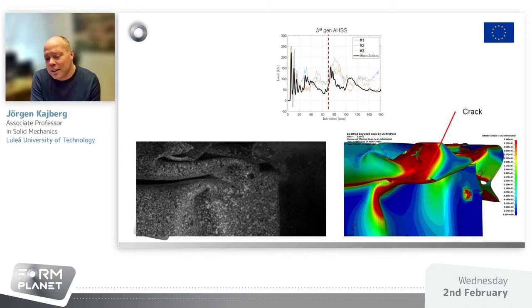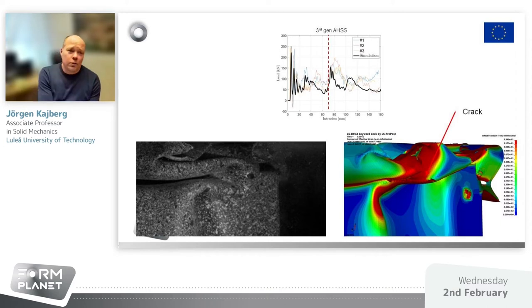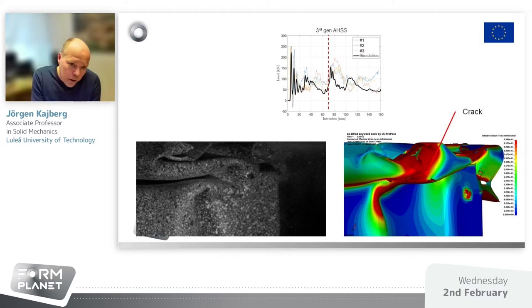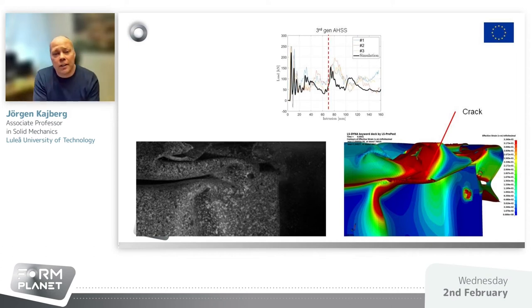At 70 mm of intrusion, you can see crack formation in the model, but you don't detect the same crack in the real components. That's what we think is the reason for underestimating the energy absorption — the material was in reality a little bit better than what our model was showing. To conclude: the ductile damage model works fairly well for edge cracking but it is recommended to combine it with another criterion, for example the forming limit diagram. The step-wise model method works well for flow stress description from initial yielding all the way to failure, and future work will aim to use the fracture toughness value directly in the material model instead of an inverse modeling procedure.